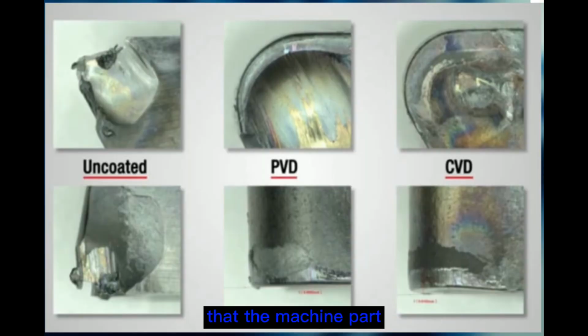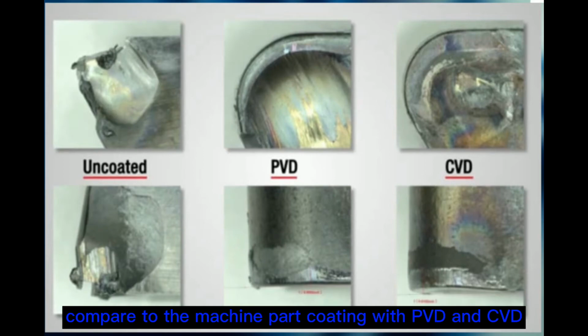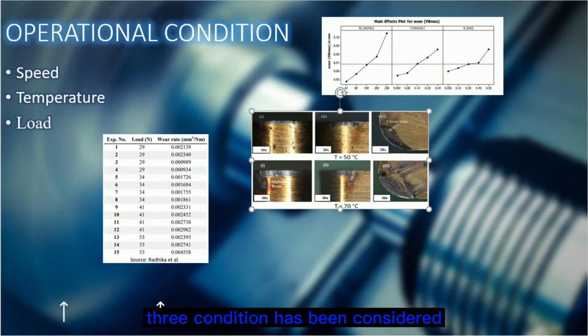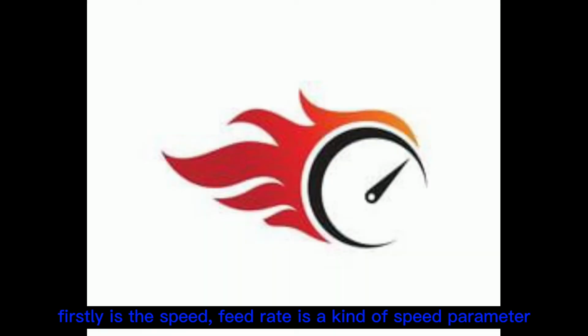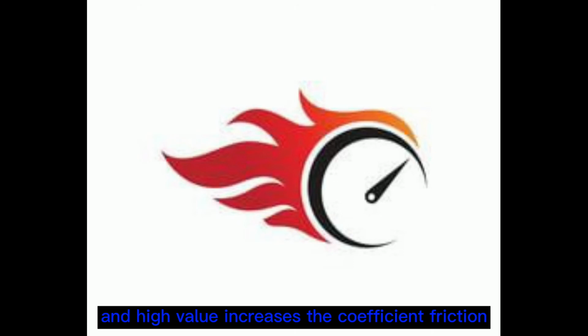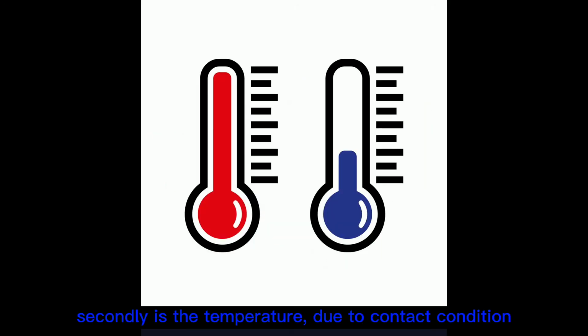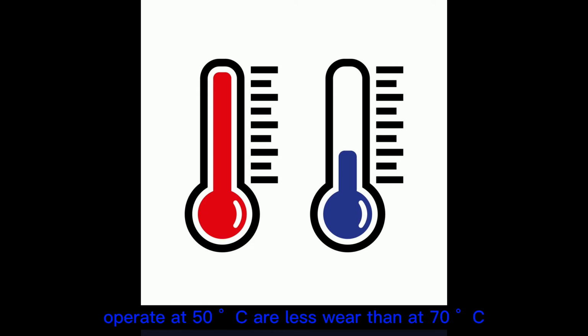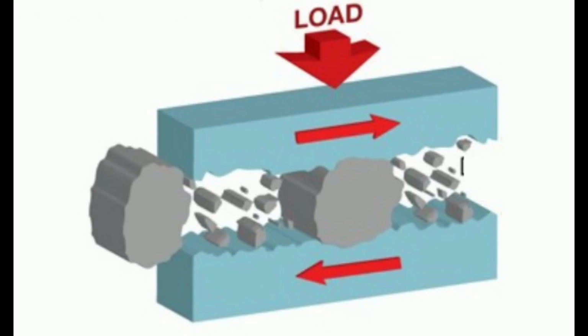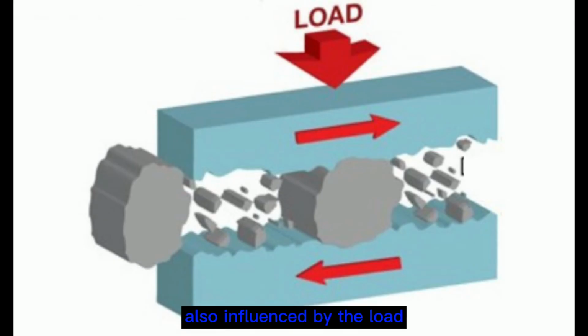The figure shows that the machine part with no coating has more wear compared to the machine part coated with PVD and CVD. For operational condition, three conditions have been considered. Firstly is the speed. Feed rate is a kind of speed parameter and a high value increases the coefficient of friction, which accelerates the wear rate. Secondly is the temperature. Due to the contact condition, heat accumulates on the machine part and deteriorates the material's structure, which produces stress. We can see from the figure that the machine part operating at 50 degrees Celsius has less wear than at 70 degrees Celsius. Lastly, the abrasive wear is also influenced by the load.